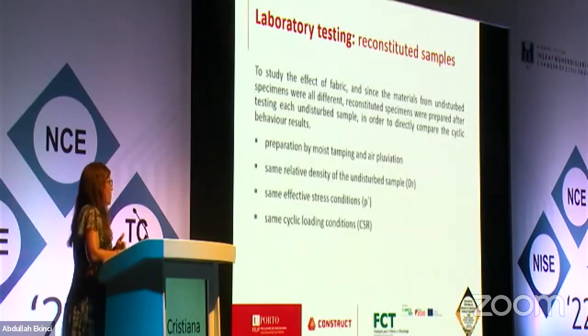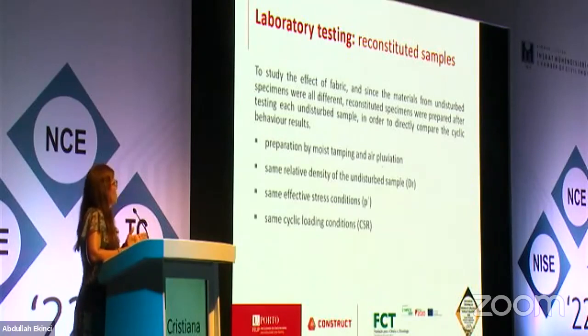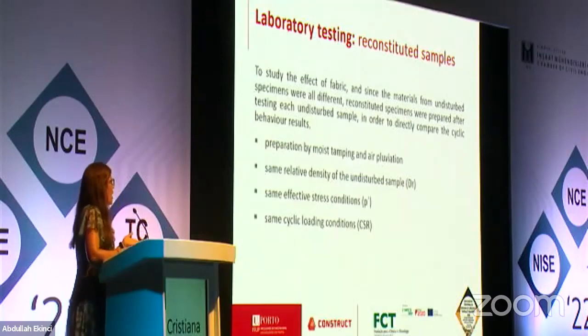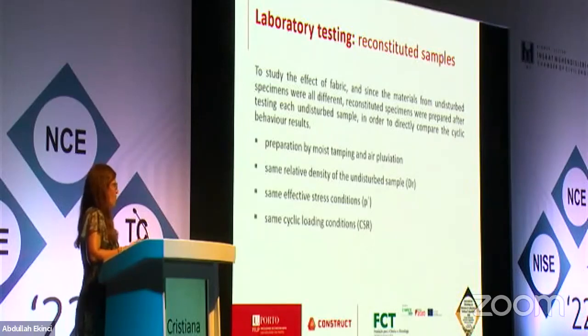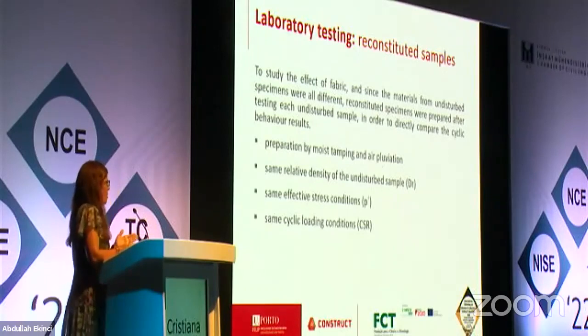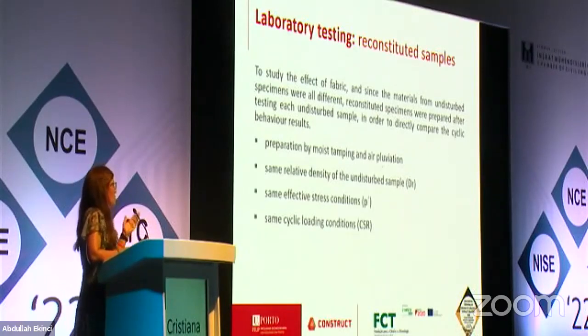After the undisturbed samples testing, we prepared reconstituted specimens with the same soil to see how this compared with the undisturbed sample. And to do that, we prepared the specimens either by moist tamping or air pluviation. We found that moist tamping was more suitable to ensure the right relative density that we had on the undisturbed samples. And this was important to eliminate the variability and the dispersion of results. We obviously tested them at the same stress conditions and using the same cyclic loading conditions, which were determined from the design values that apply to that specific site.